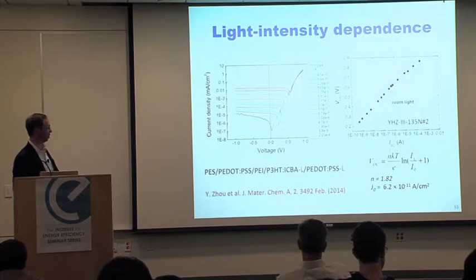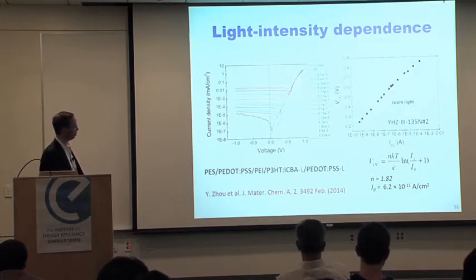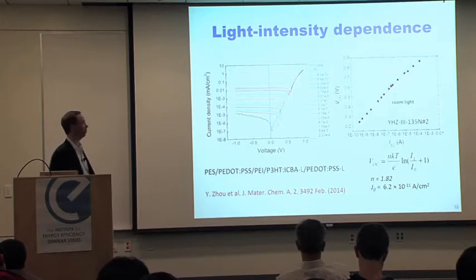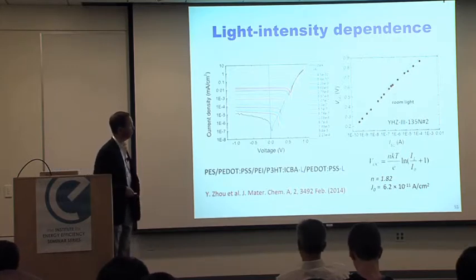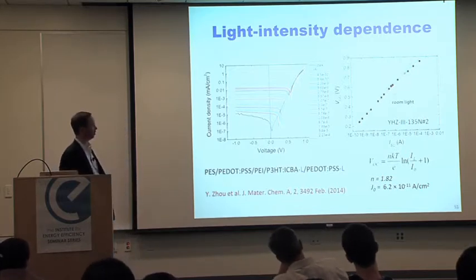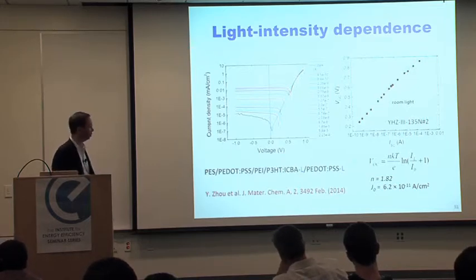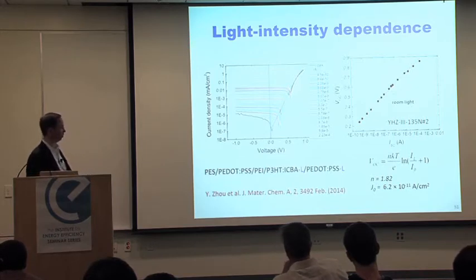Okay, and so this is again VOC versus the current or the light in these all transfer laminated devices. You see you can fit very well that Shockley diode equation over 6 orders of magnitude. And then from that slope also you can calculate the ideality factor of your diode, which gives you information about the type of recombination.